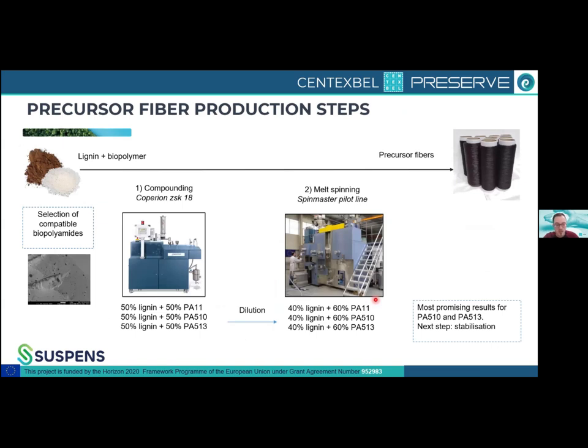Here's some technical information about this, like how are we doing it, how much percentage can we go to, and really we see that we can go up to 40% of lignin already in the melt spinning one. By compounding, we already can go to 50% lignin, but then when we try to do that, we have to dilute this into the melt spinning line that we have at Centex because it is too difficult still to do 50% of lignin.